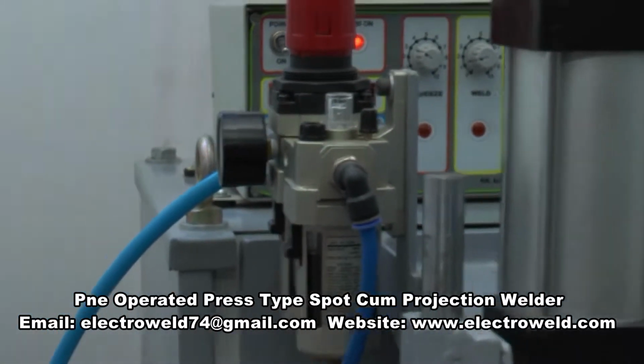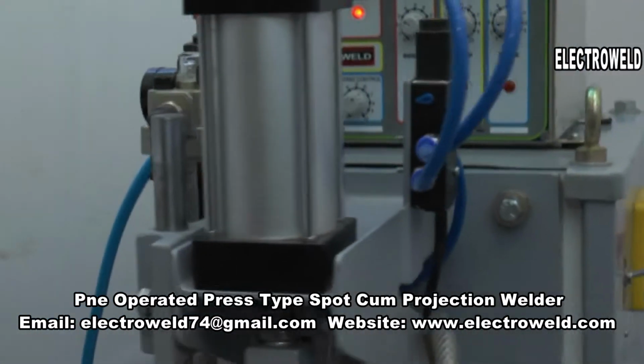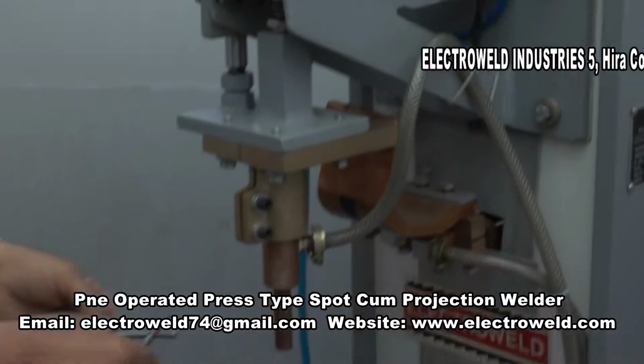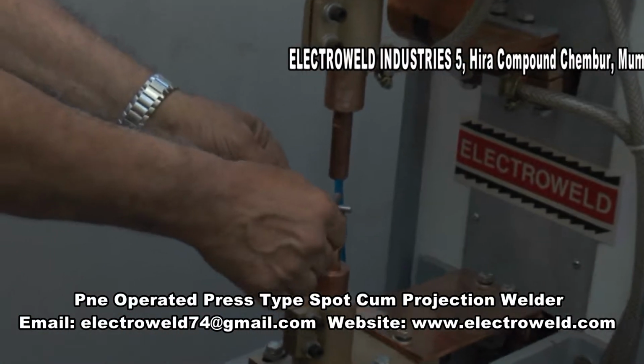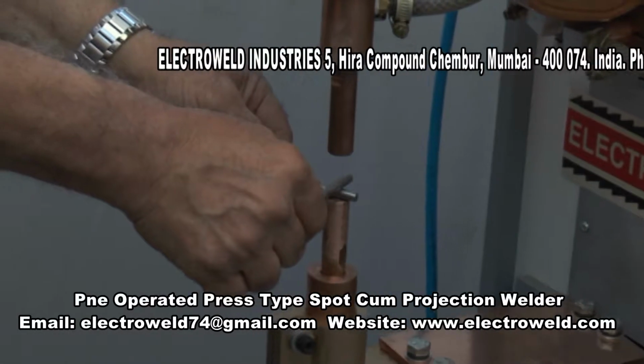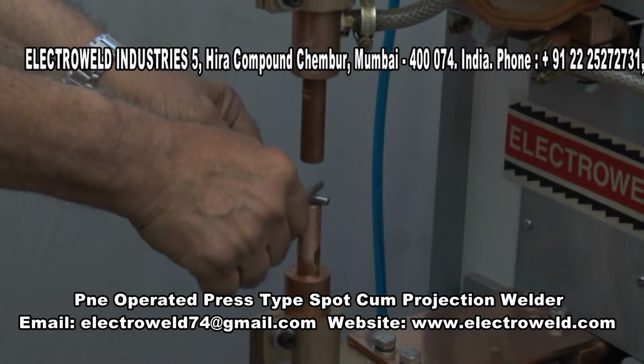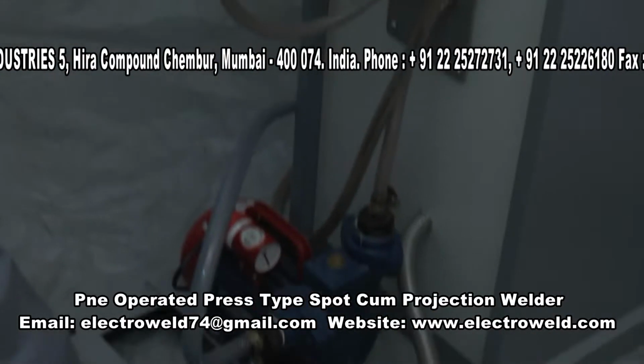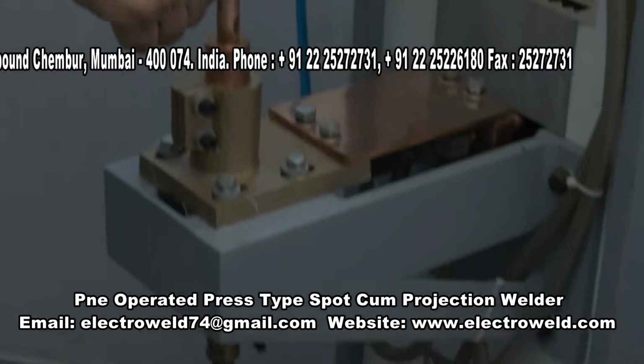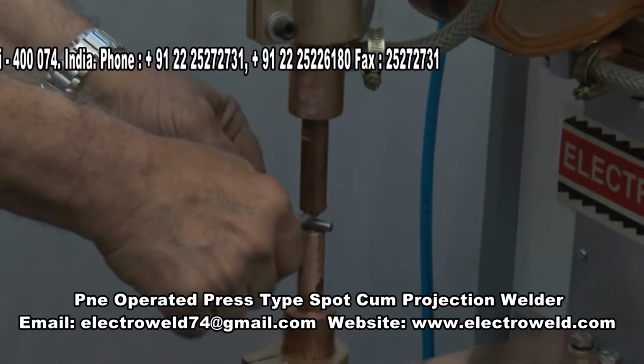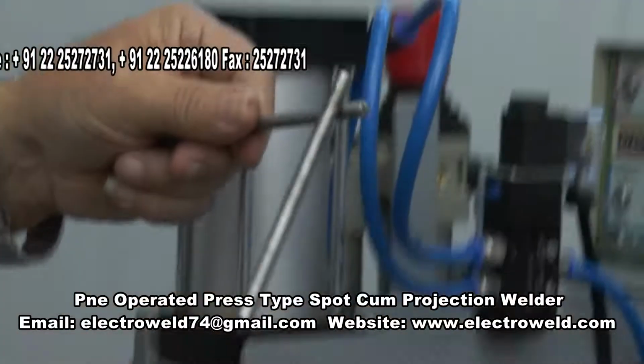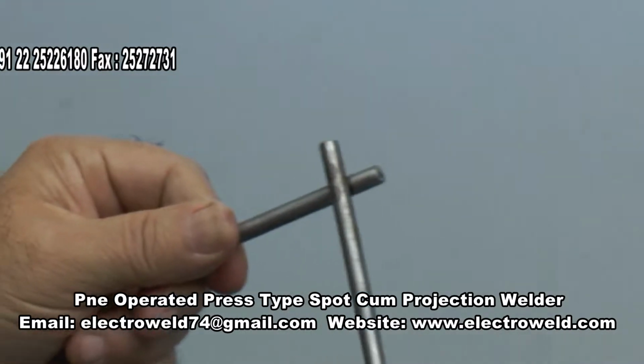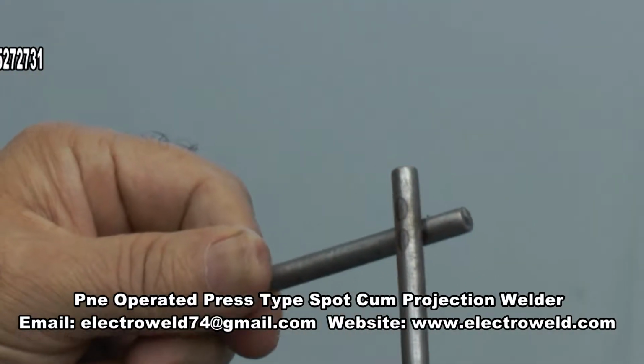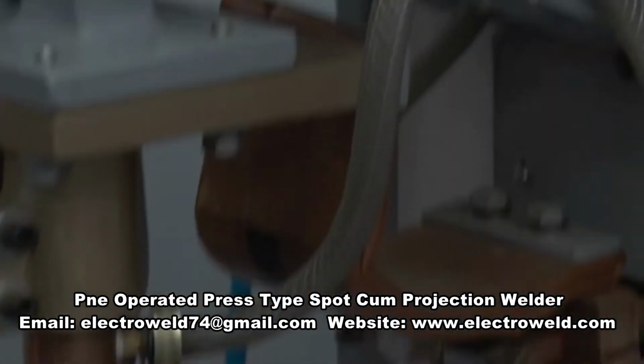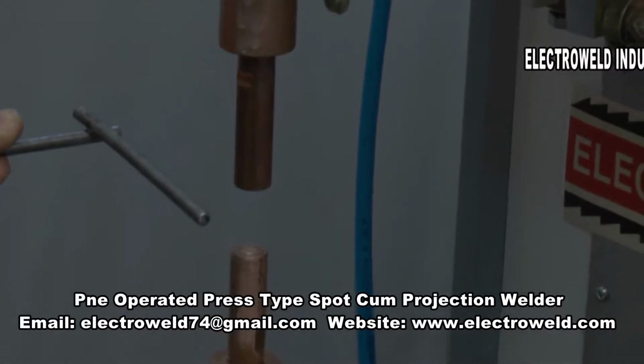Now we can show you the welding of 6 mm plus 6 mm SS wire rods by putting the 2 rods between the 2 electrodes, which are both flat electrodes, and then by pressing this foot switch you will see the welding will take place and the current cutoff will be automatic. See, this is how it is welded. You can keep on welding kitchen wire baskets by changing the distance of the job. Thank you.